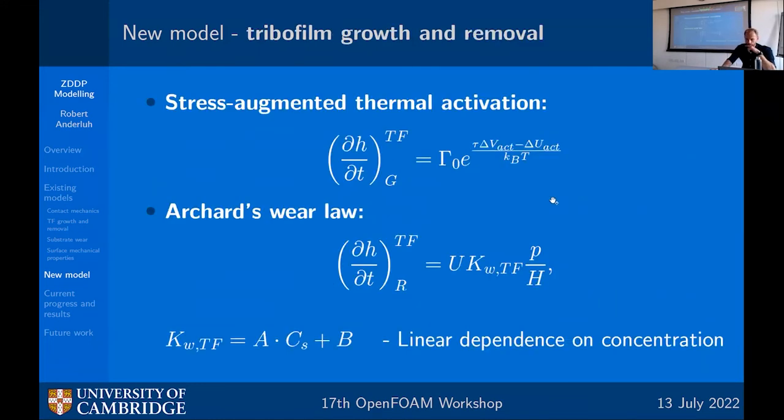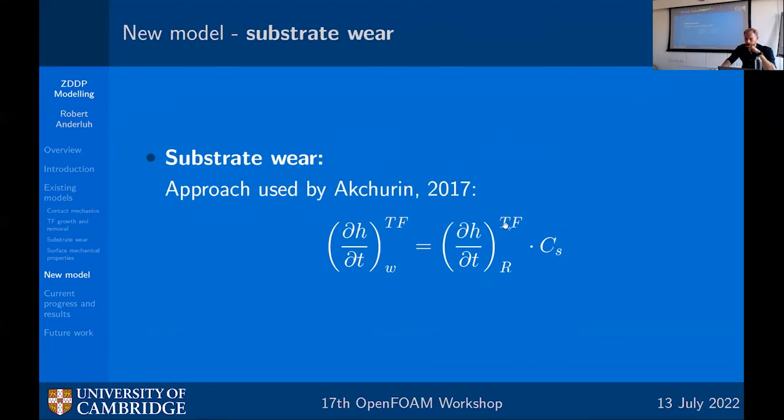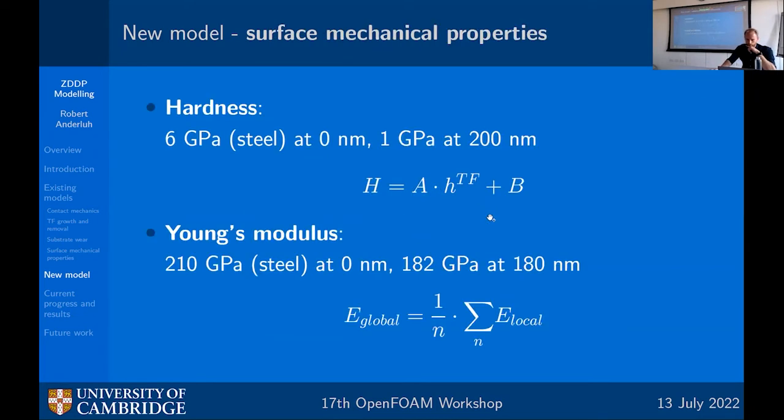Regarding the tribofilm growth and removal, this has been used by other authors, and given the state of the art of experiments, this is a good assumption, a good approximation for how tribofilms grow. Archard's wear law is a good way to model the removal of the tribofilm, and then from there, similar to the approach by Akchurin, we can use that to get the removal of the substrate, which would be present in a certain concentration throughout the thickness of the tribofilm.